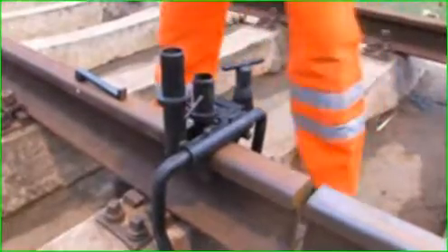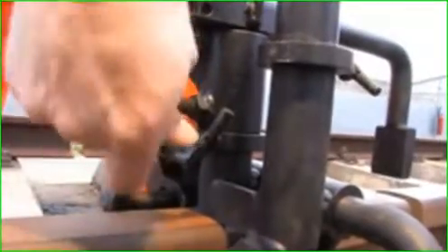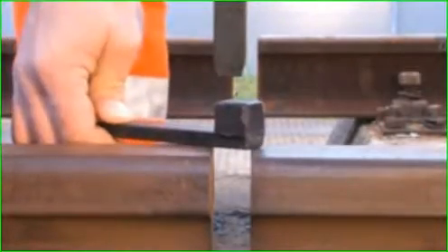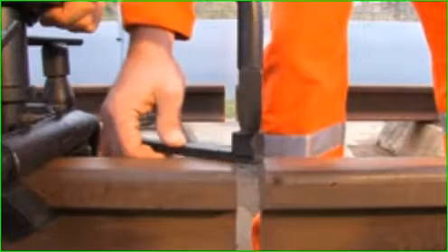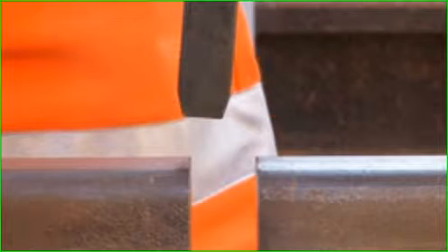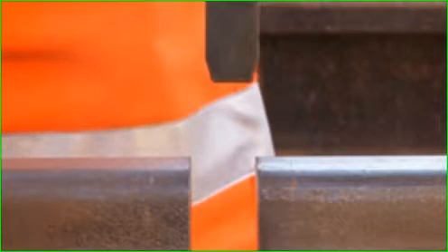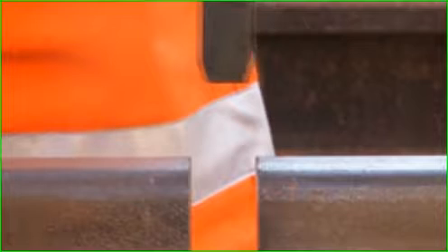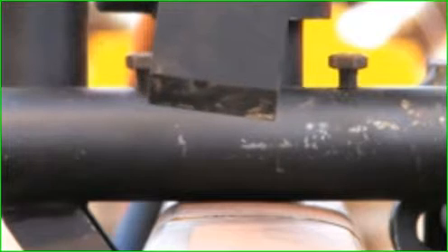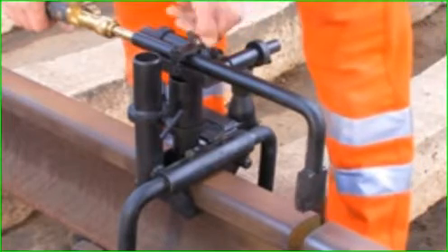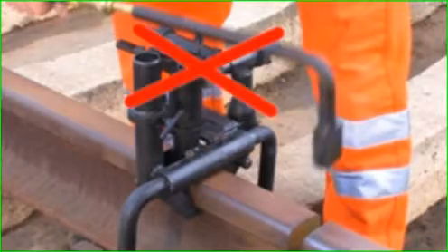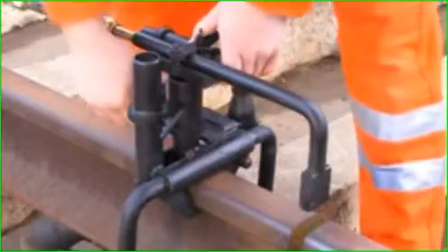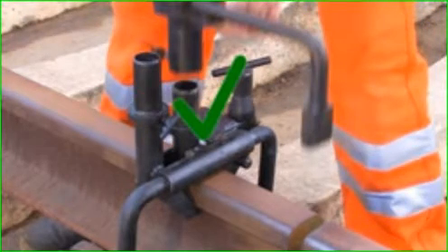Still, before the later setting of moulds, the preheating torch with the burner saddle is to be adjusted over the gap. For this, you must first set the correct torch height, by using the setting gauge, that means the distance of torch to the running surface. For the purpose of uniformly covering both rail cross section areas by the flame, the preheating torch, inserted into the burner saddle, is carefully to be set both centrally to the gap and at right angle to both rail axes. As from now, the correctly positioned torch must not be disconnected from the burner saddle, but only together with the burner saddle can you remove it from the clamping device.